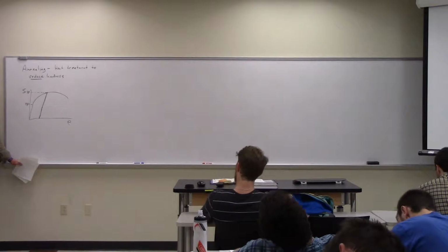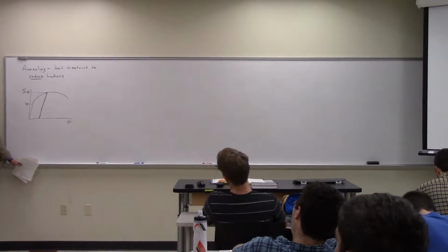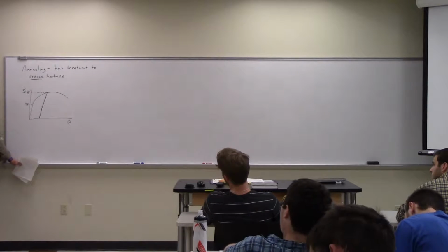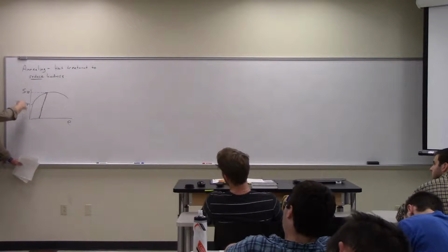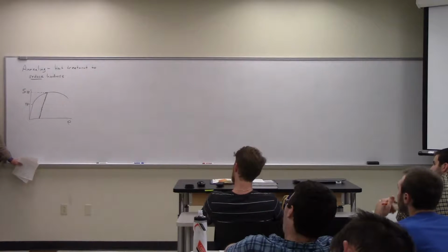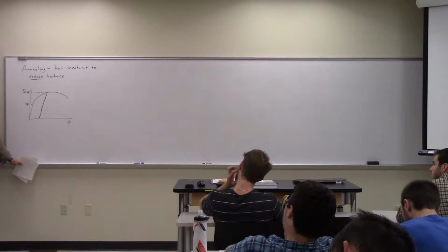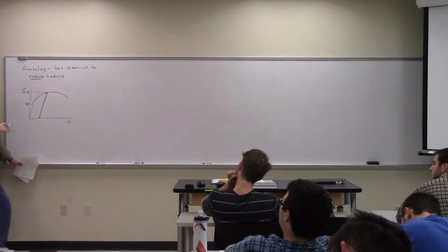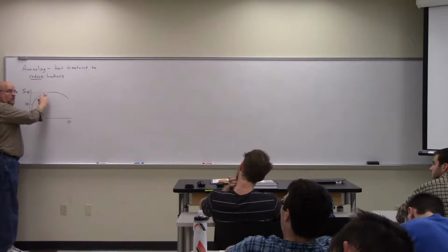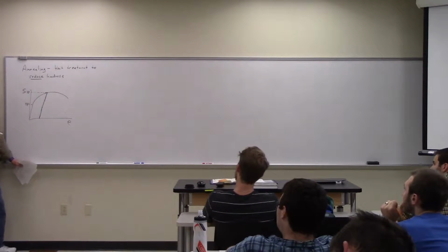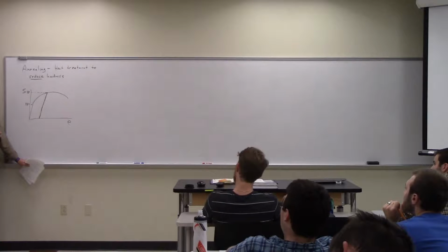Does that make sense? Isn't it because it messes up the internal structure? It makes it more random. So what's actually happening is you've got a whole bunch of dislocations that have piled up in the material, and so you can't propagate more dislocations, because those dislocations that you've already created are inhibiting the propagation of further dislocations. They're straining the lattice to prevent you from being able to propagate more. So you have to go to an even higher load to get enough strain in the lattice to propagate past those. Does that make sense to everybody?